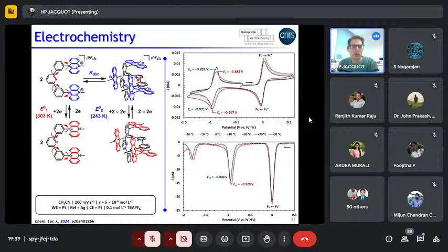If you complete the square scheme analysis, you can estimate a binding constant between the reduced chemical species, and the new binding constant is 3 times lower than it is for the native form. So in other words, when you add electrons to the acridinium cores, you will enrich them, and then you are going to dissociate the assembly.